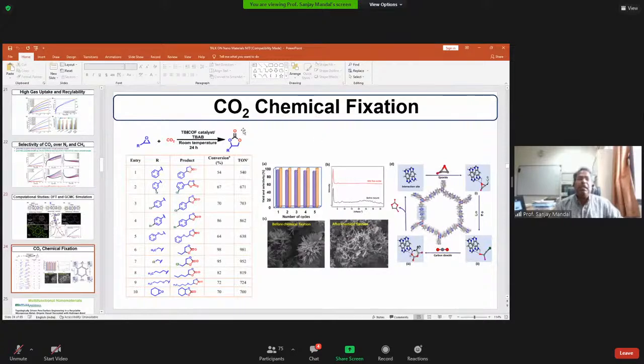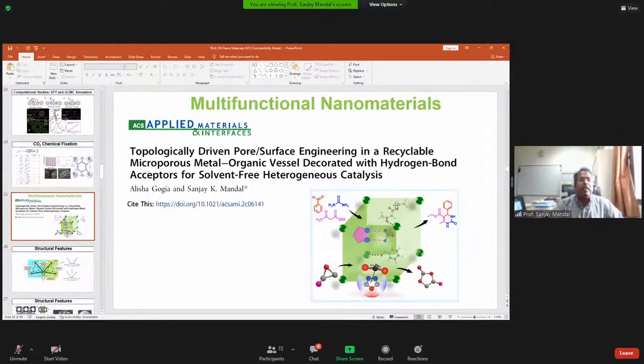And for chemical fixation to the cyclic carbonate, we have done a substrate scope, and you can see that here 98% can be achieved when you have the methyl, and 95% when you have the chloro. And we have looked at its recyclability and stability before and after catalysis through PXRD as well as AFM. The mechanism can be seen in the paper, but basically the bromide opens the ring and then CO2 gets activated to give the cyclic carbonate.